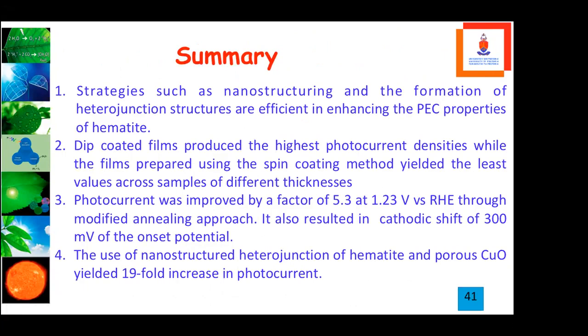I want to say in summary, if you want to use hematite, strategies for nanostructuring are very important. And there is dip coating, and the photocurrent measurements improve as you use these different strategies. And we believe that with heterostructures with copper oxide, now that we have established that copper oxide is stable, we can do much better. I call it CuO, copper oxide, that way because I'm not a chemist. I continue to do all those wrong things.